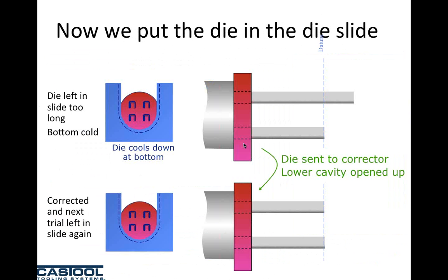We get into a lot of die correction as well, and we find that probably about 90% of all die correction is correcting the die for temperature, not because the die was made improperly. Even if we take the die perfectly from the die oven, sit it in the die slide, and leave it there for 3 to 5 minutes, the bottom of the die is going to lose more heat than the top through conduction between the die and the die slide. So your nose piece, or if you're running a 2-hole, the top holes are going to go faster than the bottom holes.